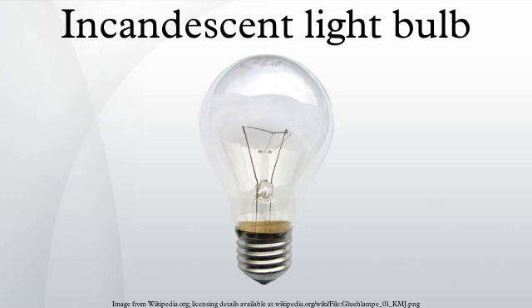For example, a 100-watt, 120-volt lamp will produce about 17.1 lumens per watt. A lamp with the same rated lifetime but designed for 230 V would produce only around 12.8 lumens per watt, and a similar lamp designed for 30 volts would produce as much as 19.8 lumens per watt. Lower voltage lamps have a thicker filament, for the same power rating. They can run hotter for the same lifetime before the filament evaporates.